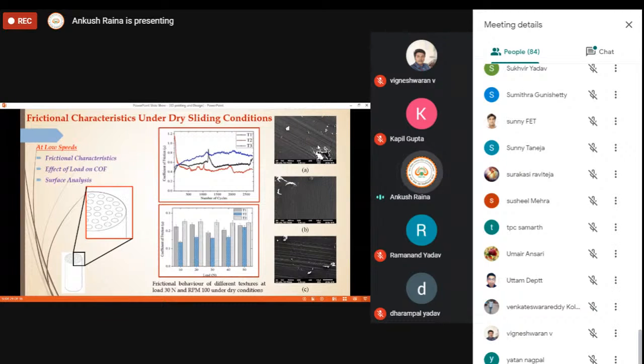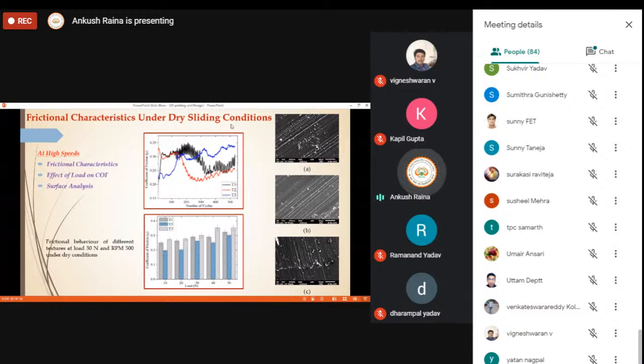Now coming towards the frictional characteristics under dry sliding conditions, but these are at high speeds. If you take into consideration the high speed characteristics, you can again see the frictional characteristics over here. Texture T1 has shown varied behavior, whereas texture T2 has also shown some different behavior. At the start, the coefficient of friction is high, but it certainly decreases after steady state, after 200 cycles, and tries to stabilize. Whereas for texture T3, the coefficient of friction increases, and is more in comparison to the previous cases. If you take into consideration all these coefficients of friction at different loads, again texture T2 has proved to be a good texture, which has resulted in the minimum coefficient of friction.